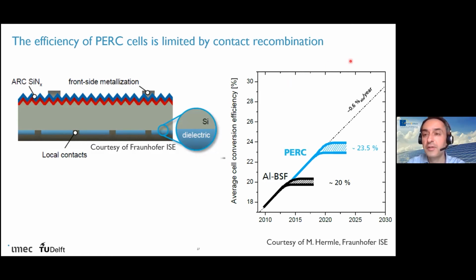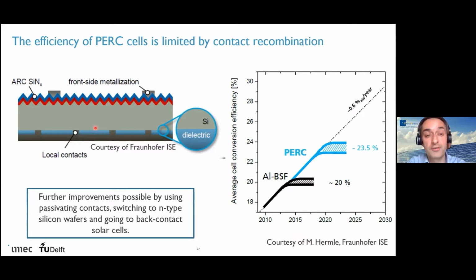That's still where the main limitation comes from. So if we look at the potential for the PERC cell - these are curves I took from Fraunhofer ISE from the past - we can say that in industry with aluminium BSF cells, it has been shown we can reach around 20% cell production. With PERC cells, and this is already happening a little today, we expect industry can produce cells up to 24% probably. But then again you are limited, and the limitation comes really again from the surface at the rear.